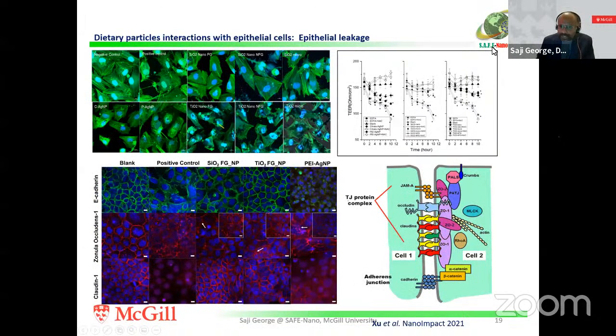And we can look into why that is caused. We can look into the molecular interactions between the proteins, and we can see that some of those proteins that are involved in the tight junction as well as in the adherent junctions are affected. Especially what we see is with the cationically charged silver particles, all these classes of proteins are affected, which means they are retreating into the cytosol, which means they are no more adhering properly. But with the silica and titanium dioxide, we see a major effect on the tight junction, but much less effect on the adherent junction, which is the E-cadherin. But they are not benign to any of those.